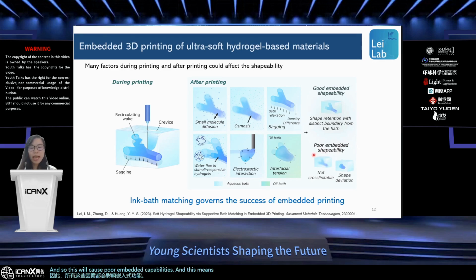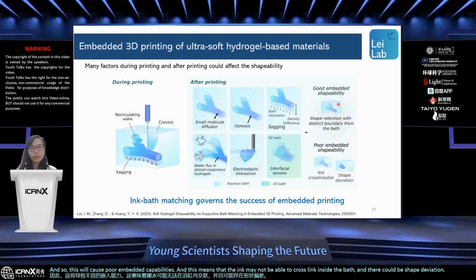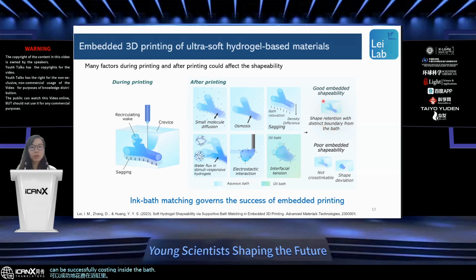This means that the ink may not be able to cross-link inside the bath, and there could be shape deviation. A good embedded shapeability means that the shape can be retained within the supportive bath with a distinct boundary, and the ink can be successfully cross-linked inside the bath. To achieve good embedded shapeability, matching the properties of the ink and the bath is very important for the success of embedded 3D printing.